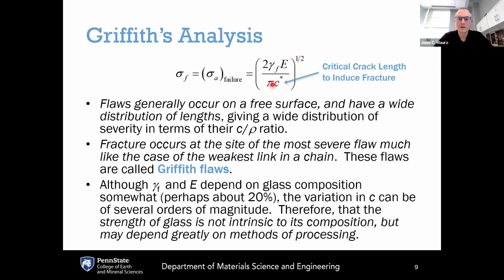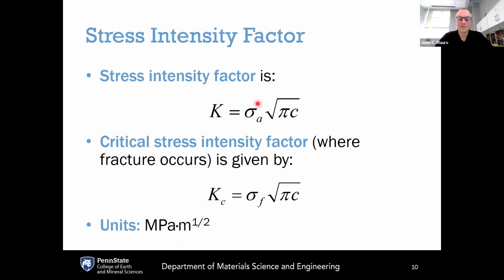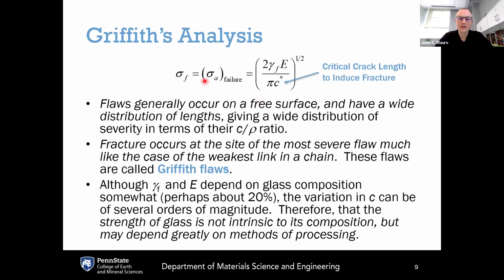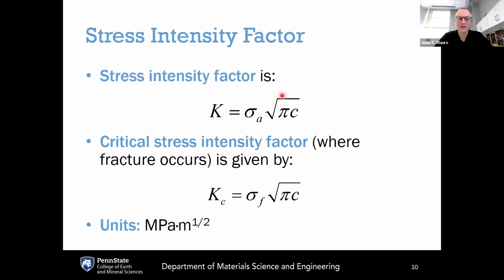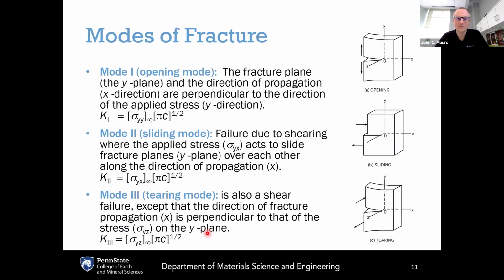And this, in the denominator here, is the square root of pi times c star. The c star is the critical crack length to induce fracture in a material. If you take this square root of pi times c star and multiply both sides, this applied stress times the square root of pi c star is what gets us what's called the stress intensity factor, or K, introduced by Griffith. And the critical stress intensity factor, which now has a subscript C, K sub C, is where the fracture occurs. And so this is given by the stress at fracture, sigma sub F, times the square root of pi C, where C is the length of the surface flaw. The stress intensity factor has units of stress times the square root of distance. Typically, these are expressed in terms of megapascals times square root of meters. The failure of the glass or brittle material can occur in different modes.